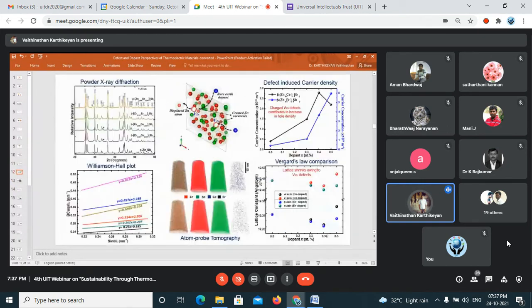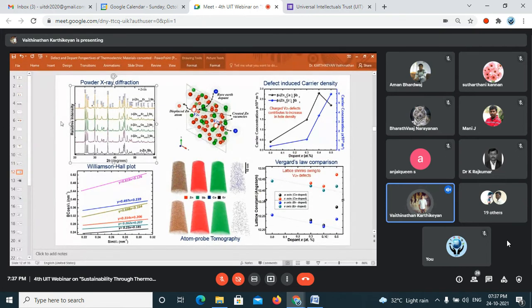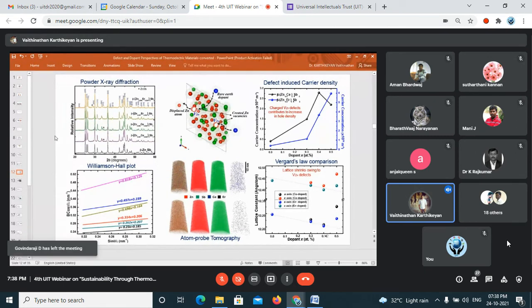Okay, the next slide is this one. This is the characterization by diffraction, I mean powder X-ray diffraction, where we see the results with different dopants. The dopants which we used are cerium and terbium, and we found the efficiency for cerium and terbium higher when compared to other materials.